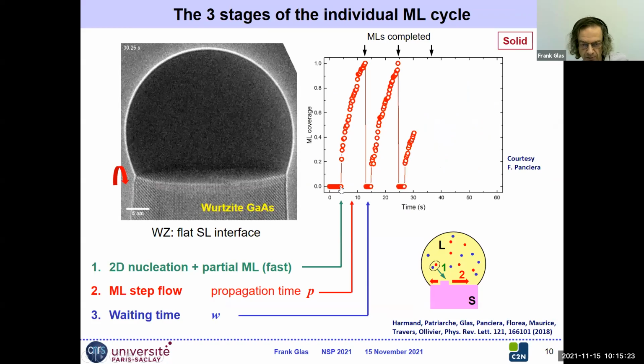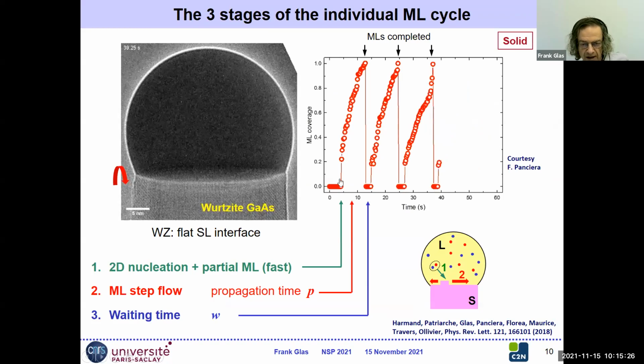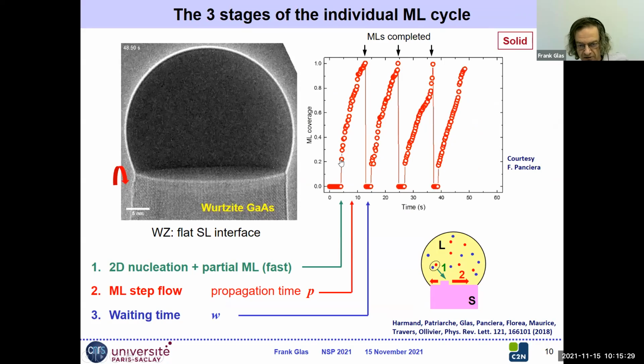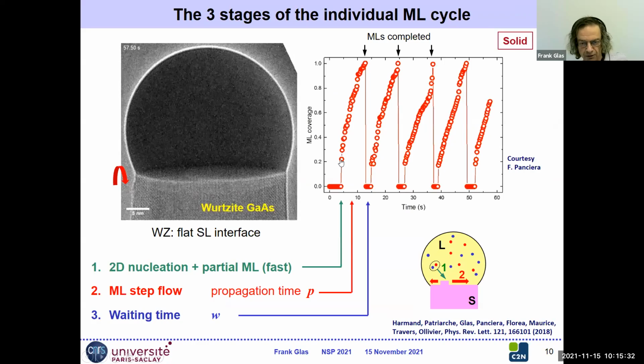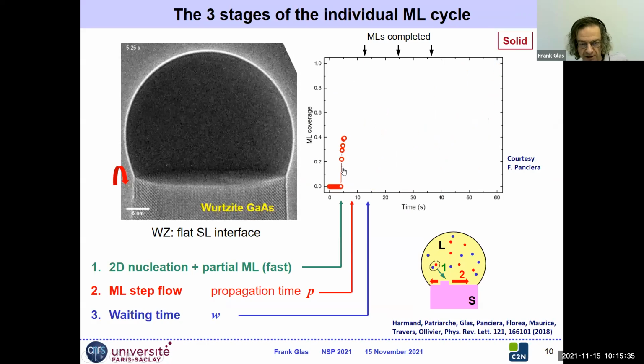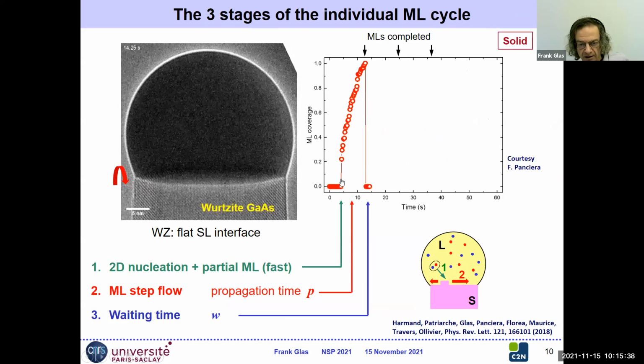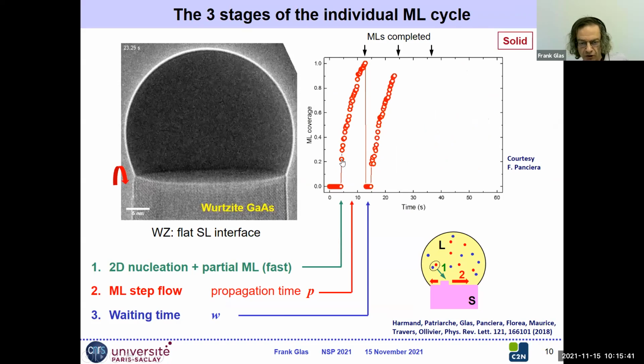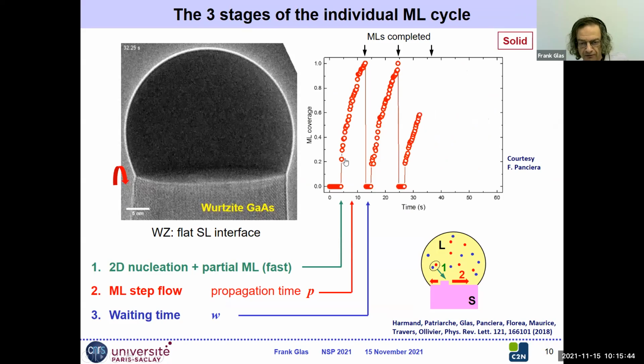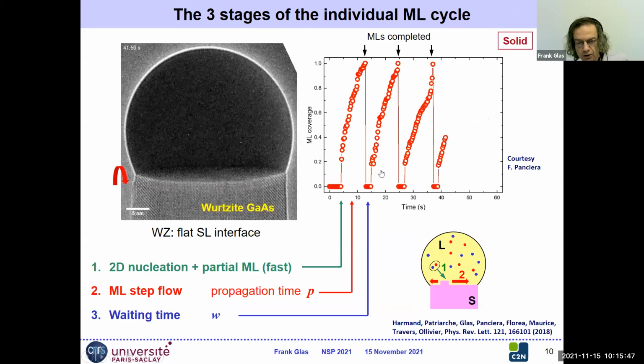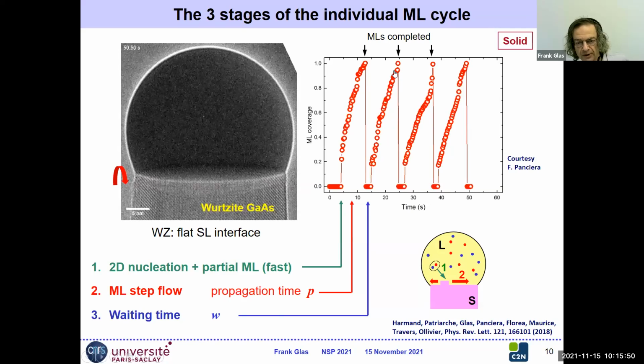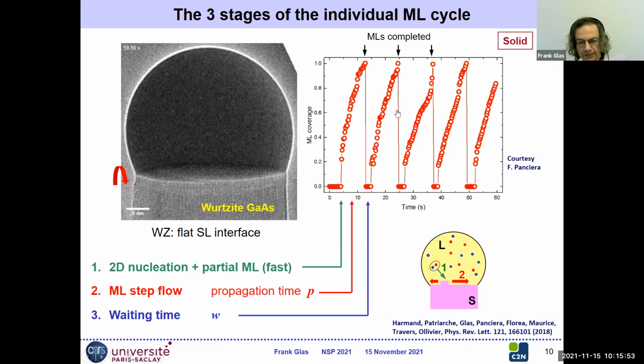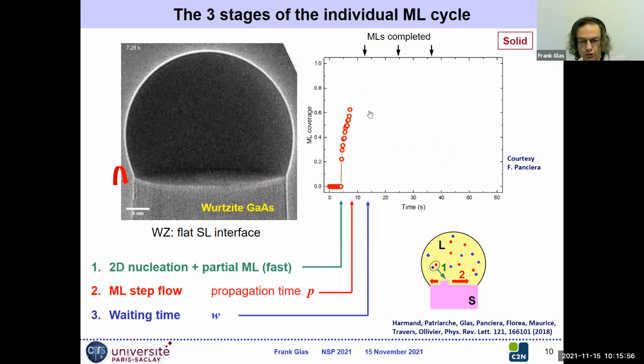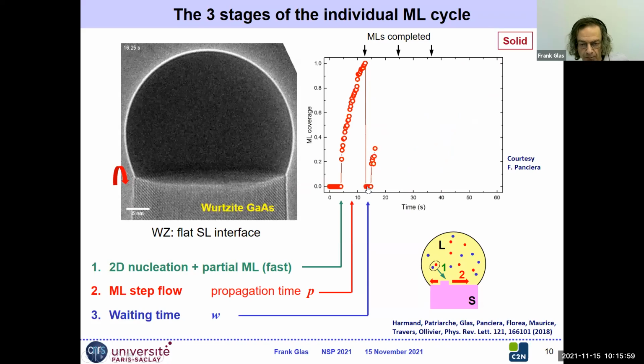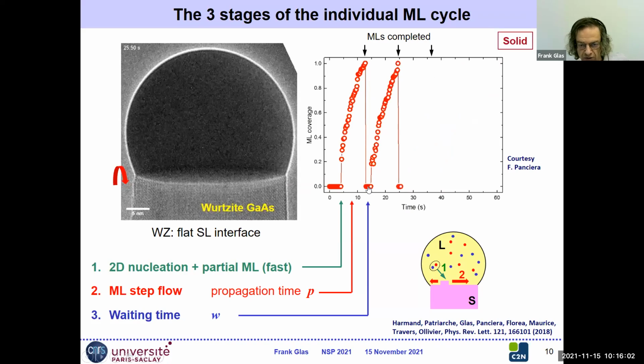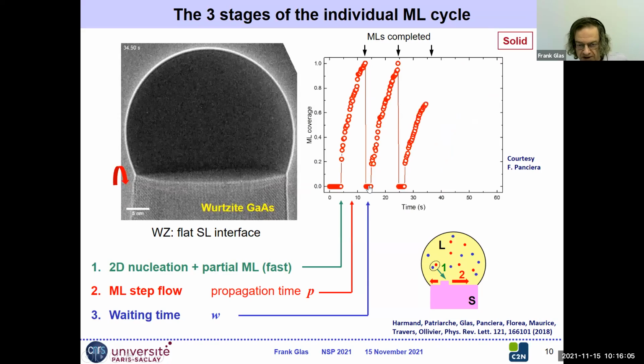It is 0. At some point here, we have nucleation, but very fast the coverage increases. It increases abruptly, but it does not increase to 1 as in our previous model. It increases to a value less than 1. Here it's about 0.2. Here we don't have sufficient time resolution to see what happens, so for us it's instantaneous. Instantaneously, we form a partial monolayer. And then the rate of progression of the monolayer is much lower. And finally, we get to a coverage of 1. And very importantly, nothing happens for some time. So the coverage remains equal to 0 for some time, which for us is the sign of nucleation.